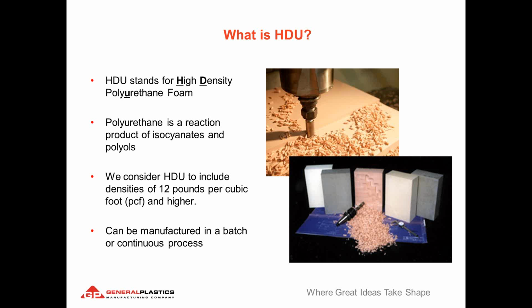And we consider HDU, the high density, to include densities above 12 pounds per cubic foot. The insulation industry, like the spray foamers, 2 pounds per cubic foot is what they call high density. So for the sake of discussion today, though, HDU is much more the high density materials from 12, and we make up to 50 pounds per cubic foot. And of course, urethanes, there's 2 basic processes to manufacture materials. One is a continuous process, which usually has set block sizes of width and thickness, or a batch process, which is much more customizable in your block sizes.